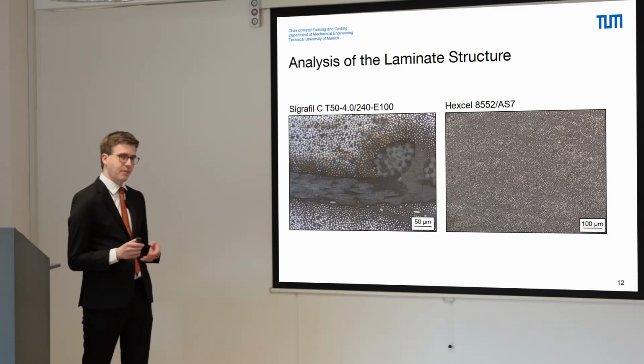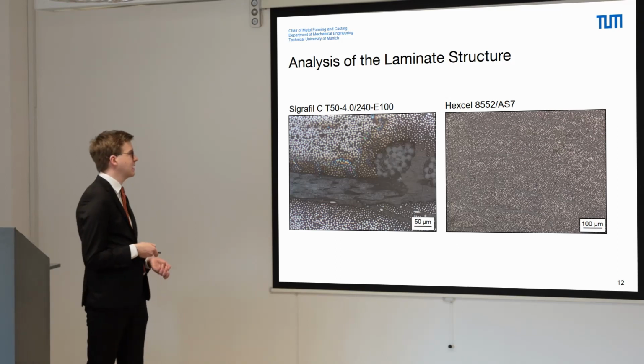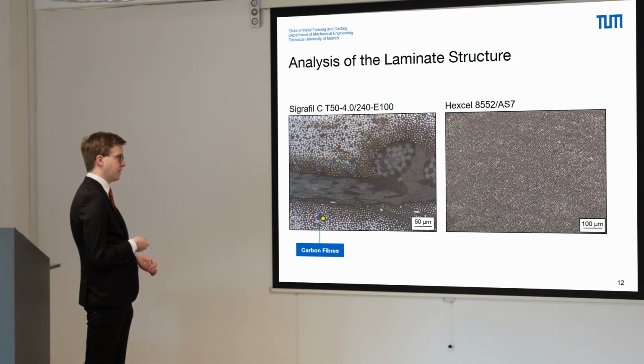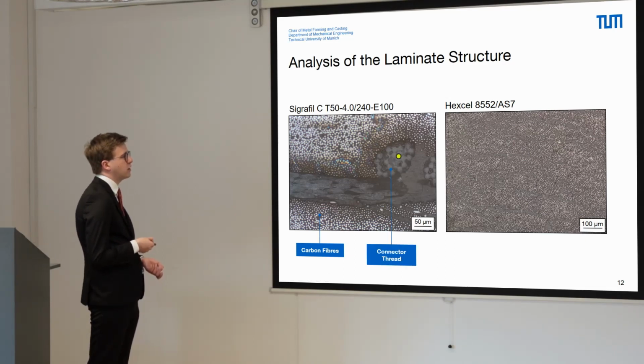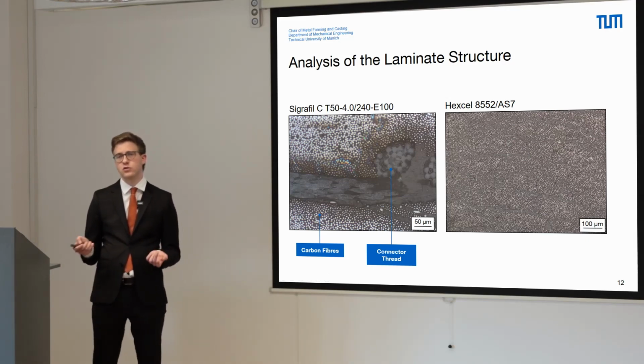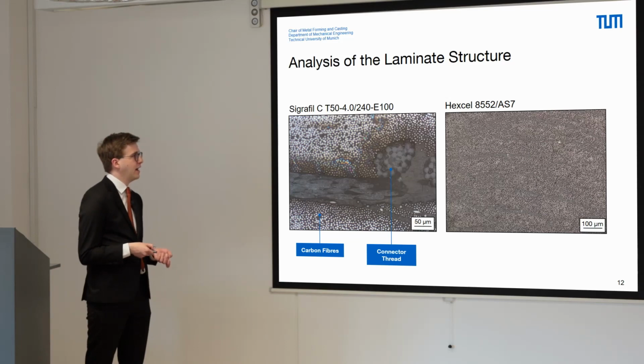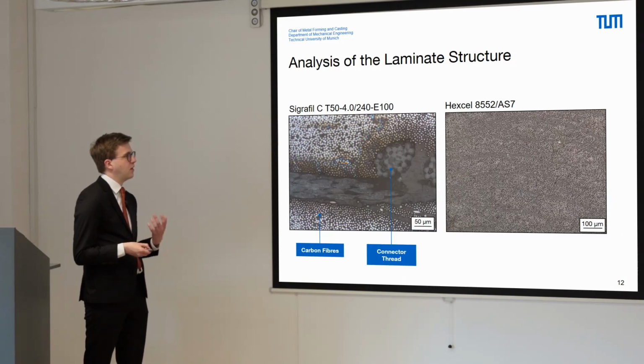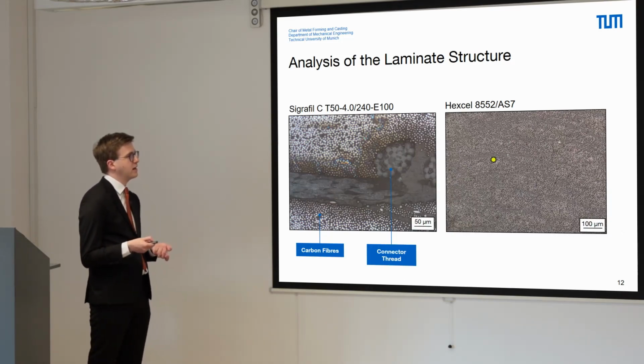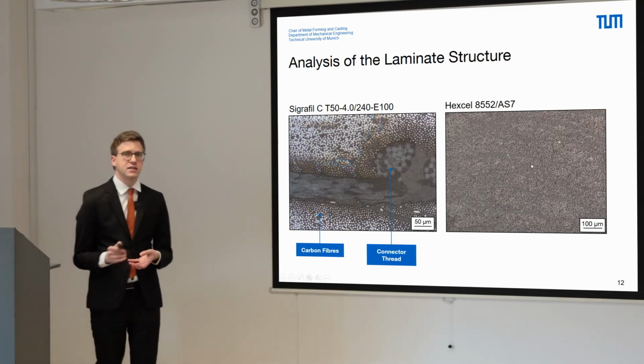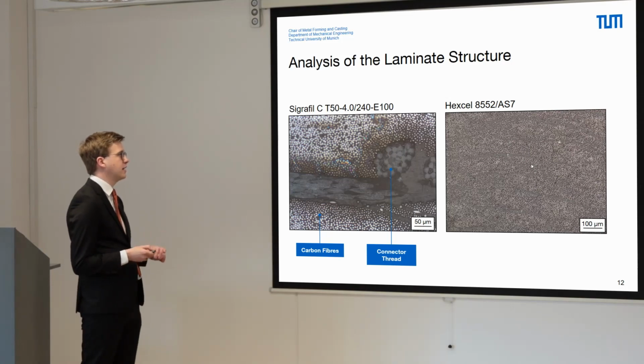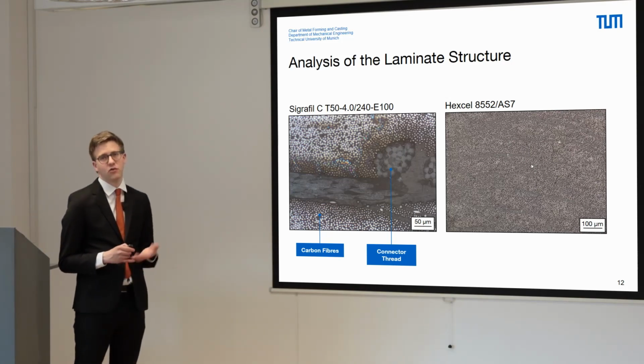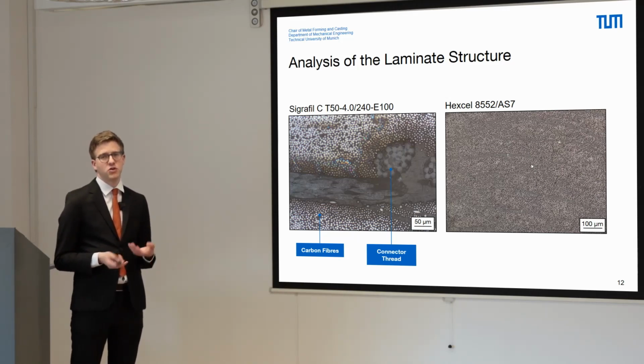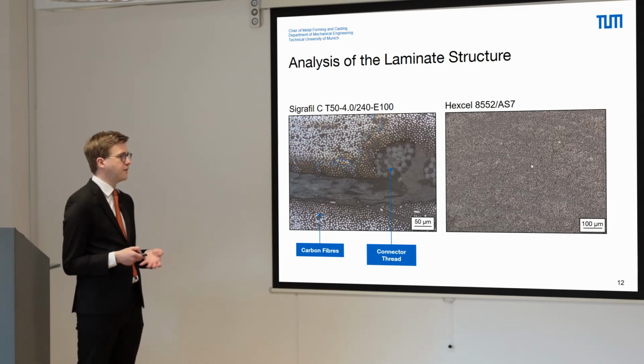When we analyze the microstructure of the resulting composite, we can see for the manual laminated sample on the left both the carbon fibers but also the connector thread, which is used to hold in place the UD fibers before the lamination process. And next to these connector thread fibers, one can see some associated porosity. Compared to the automated fiber placement strategy here shown on the right, where a much more homogeneous structure can be derived, and therefore this automated fiber placement strategy or this pre-preg based strategy is the better choice for further industrial applications of our hybrid beads.